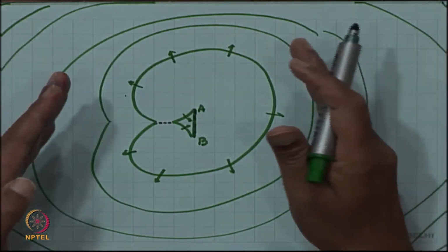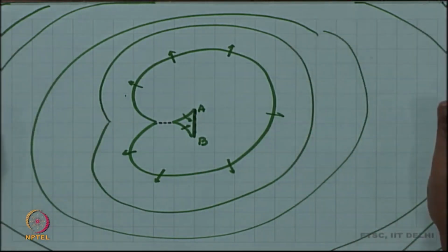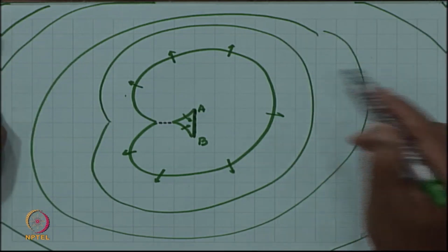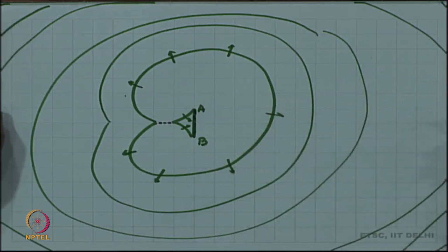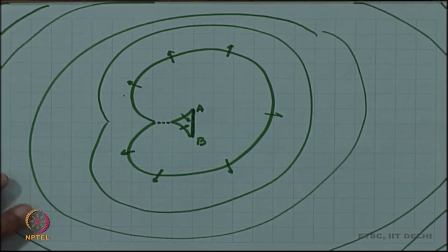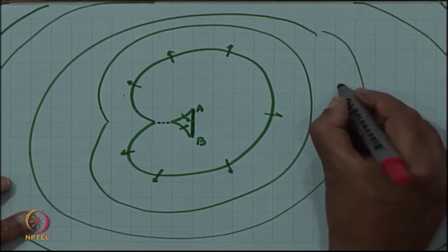But notice that although one loop has completely swept out and has disappeared, there are other loops which are coming, because this AB segment has been regenerated and can keep creating newer and newer dislocation loops. So, this is why it is called a dislocation source, and it is a continuous source for dislocation generation and is known as the Frank-Read source.